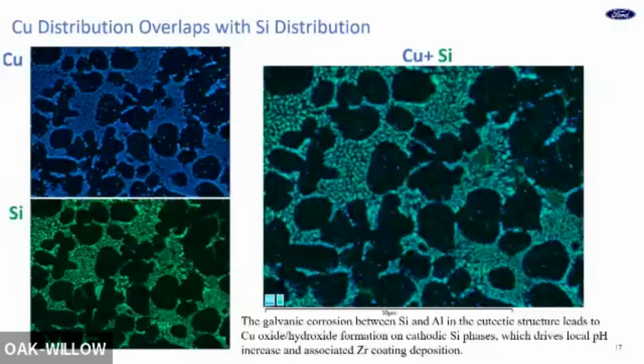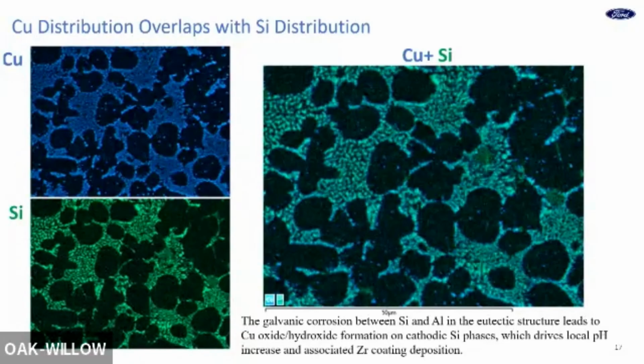But in this case, it's probably different, because if you look at the EDS mapping with the copper and the silicon, they are pretty similar. If you put these two elements in one map, they overlap very well. This indicates the copper mainly deposits on the silicon phase, and maybe there is lower deposition on the aluminum phase. I don't really see copper on the aluminum phase.